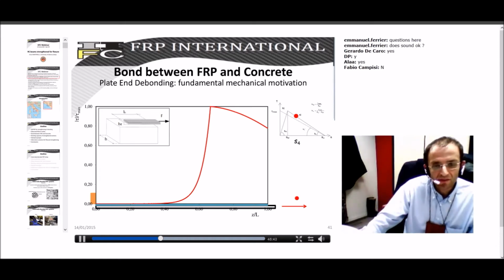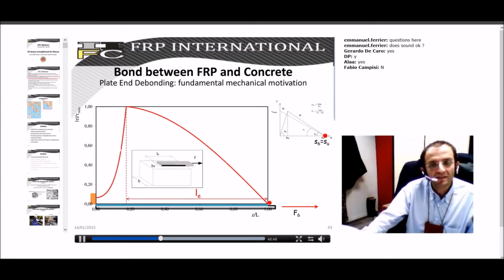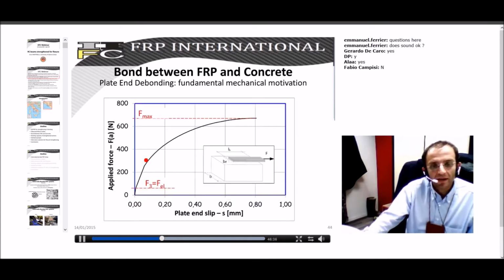So, if you proceed with this by imposing higher and higher displacement, you get to a certain moment in which the maximum displacement here is just equal to S6, is equal to SU, which means that you have here attained once again tau equal to 0. Any increase in the maximum displacement here will result in zero increase in tau. This means that we have attained the maximum interface strength, the maximum strength in terms of forces, and we have also realized the transfer length, which is the value between the maximum of tau and the point in which tau is 0. We can try to evaluate LE, or at least we can try to understand which are the parameters controlling LE, this transfer length, by this resulting applied force versus ultimate slip, which shows you what is the usual difference between the F maximum and the F elastic, which can be even equal to 10.